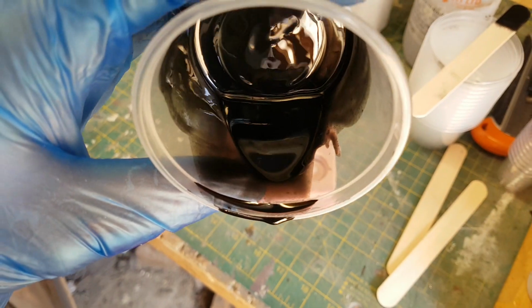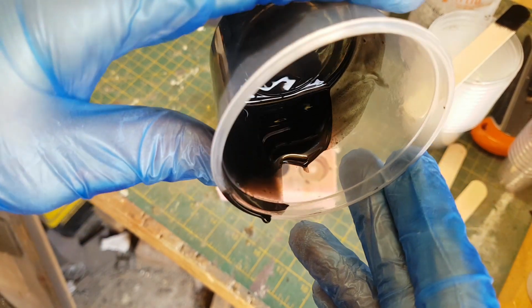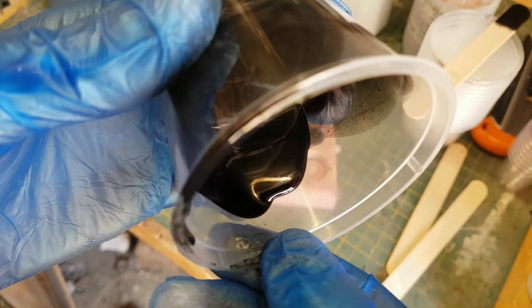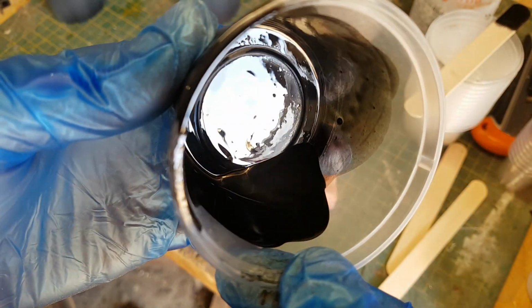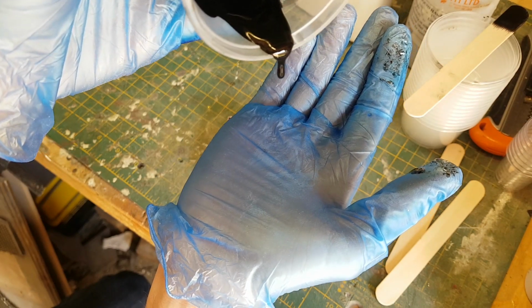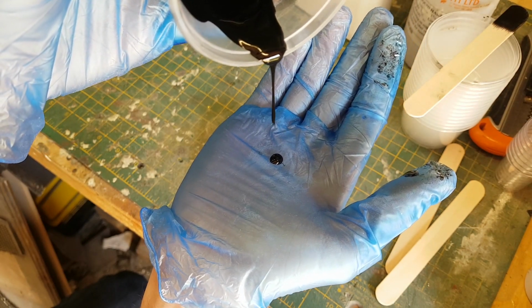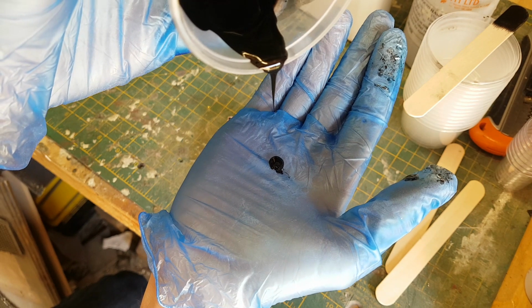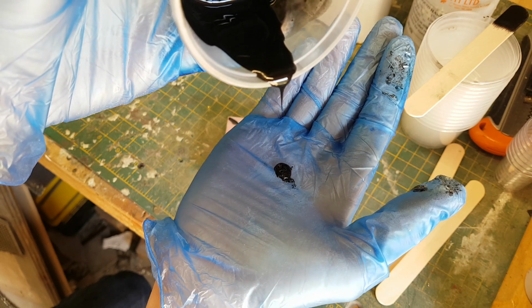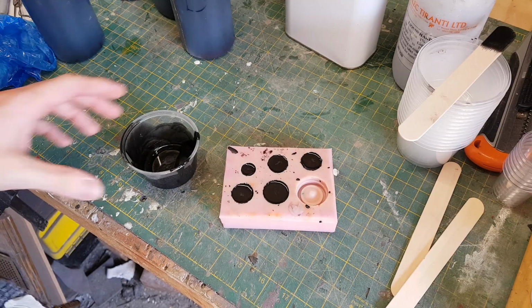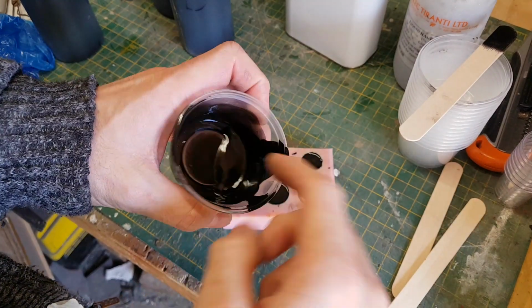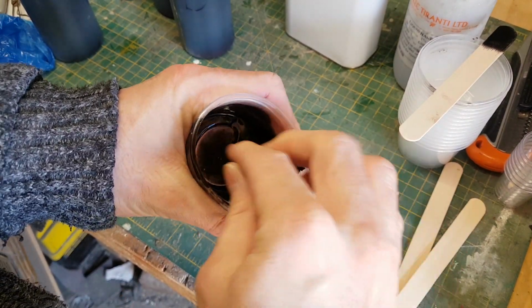As you can see, the resin's flowing about quite freely in the mixing cup here at the minute, but after about a minute or so you can see it slowly begin to slow down, and at this stage it's actually getting really, really sluggish, so I think that's about to set. Cool, so I've left that for about 10 minutes, come back, and as you can see that pulls out of the mixing cup quite nicely.